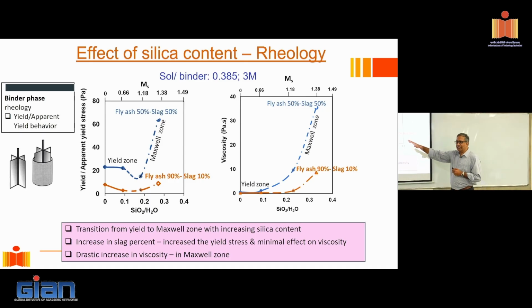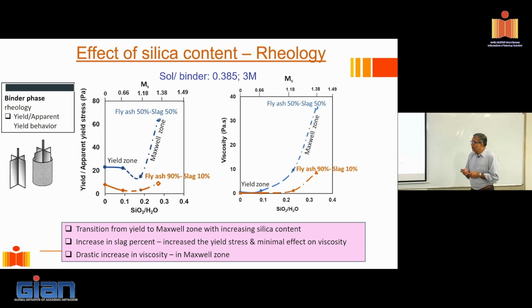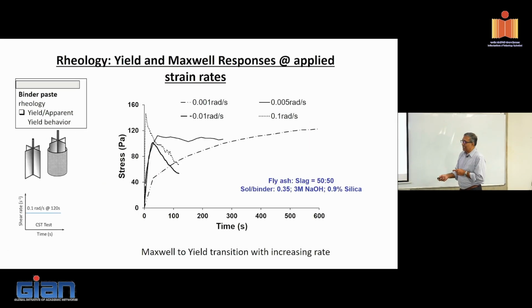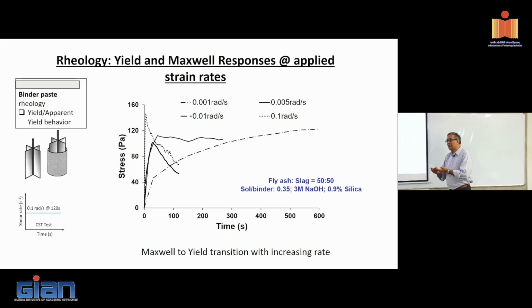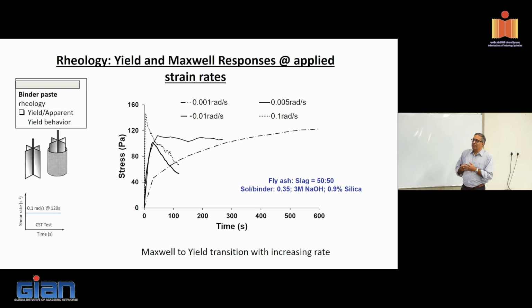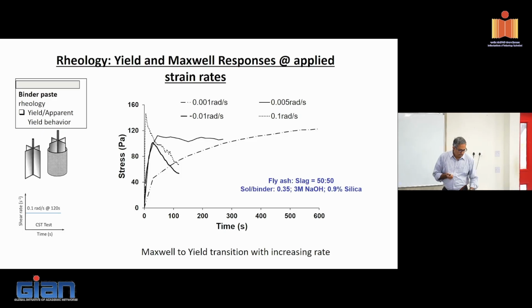See, if you hold the stress constant, it will continue to deform. I'll just show you that. So when you're doing these rheological experiments like I've shown you here, we are applying a constant strain rate. We are not pausing anywhere. But suppose I was to pause it here, right? You'll see that it will continue to deform slowly. Okay. So that is what we notice typically in these Maxwell type responses.